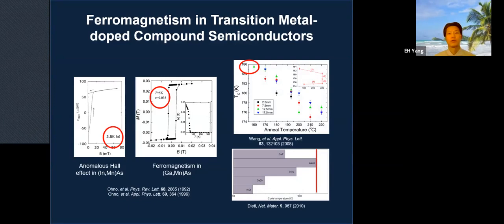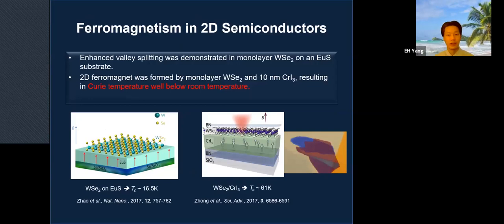Okay, now what about 2D semiconductors? These results are about just 3D conventional semiconductors. What about 2D? In 2D magnets, there were 2 papers published in 2017 using the magnetic proximity effect. So you use 2D semiconductors, which are not ferromagnets, but you put them onto ferromagnetic materials so that ferromagnetic properties are induced in these layers. Okay, and then they demonstrated this ferromagnetism, but again, one is 16.5 K, the other one is 61 K. Still a Curie temperature well below room temperature. Not only that, these are also Scotch tape methods.